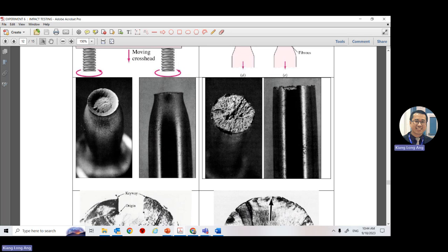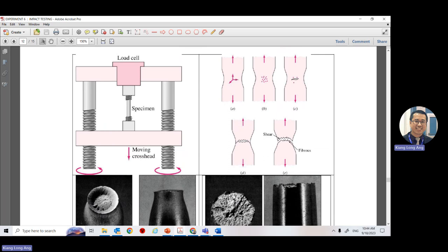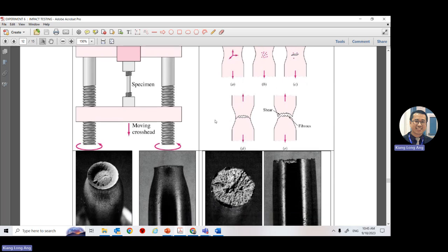You expect to see two behaviors. For ductile material, you see a cup-and-cone fracture — one piece looks like a cup on top and bottom. For brittle material, it is almost a straight flat line at the broken surface. Take photos like what you see on the lab sheet. For aluminum you can see the fracture clearly, but for carbon steel you don't know where it will break, so a video of the gauge is better.